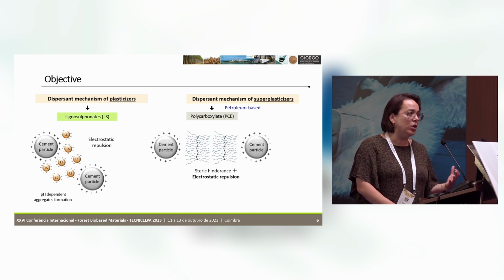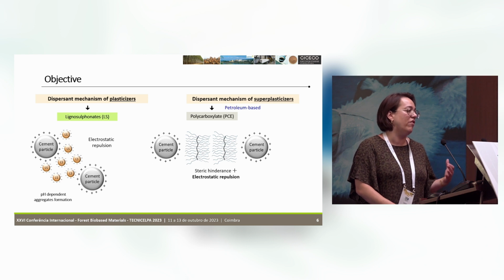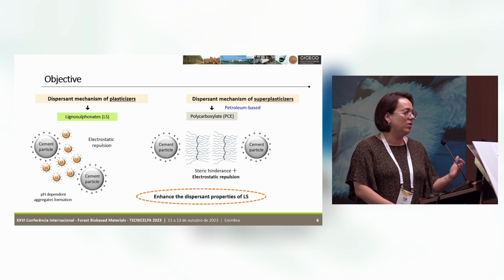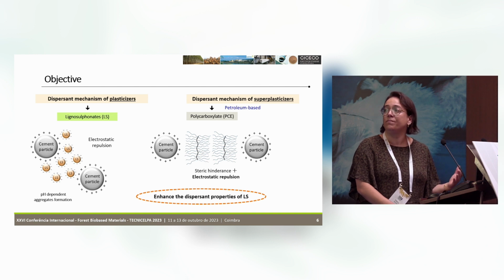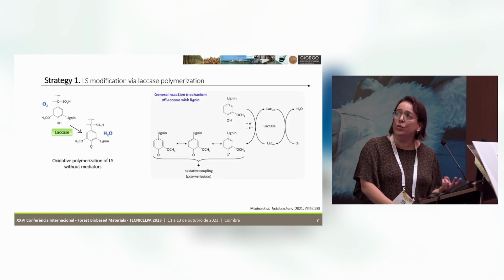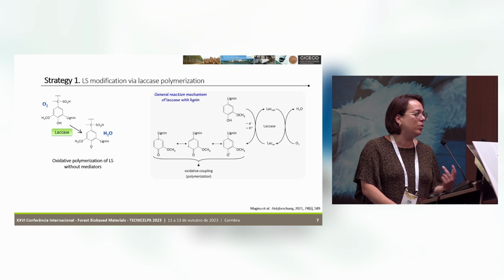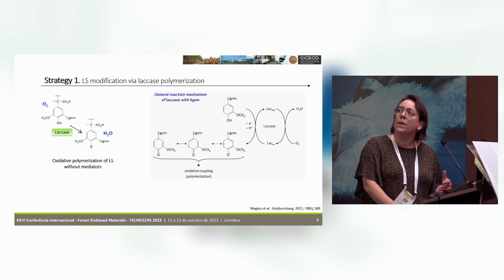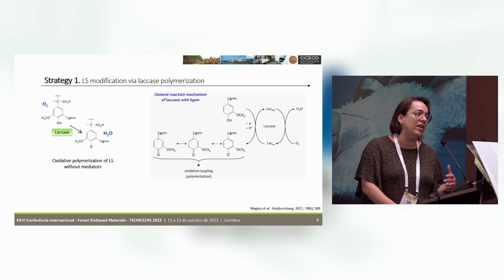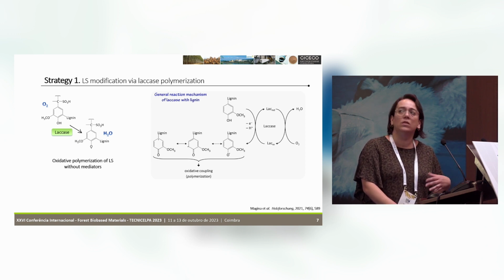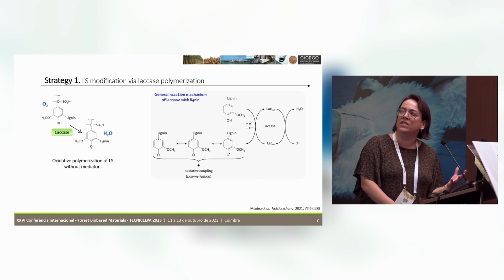So the purpose of this work was to improve the dispersant properties of lignosulfonates to approach that of polycarboxylates. Two strategies were used, and the first one, and probably the most referred one in the literature, is the increase of molecular weight by modifying lignosulfonate using laccase to provide polymerization of lignosulfonates.